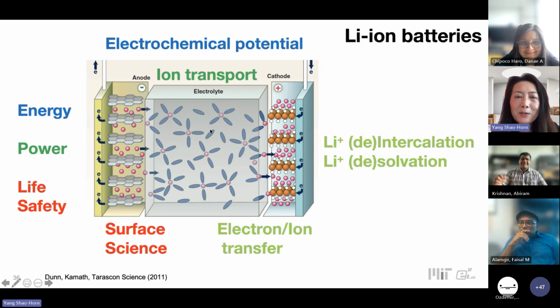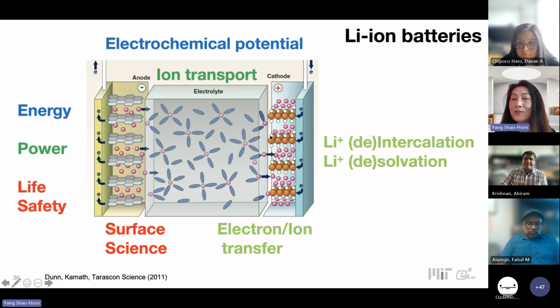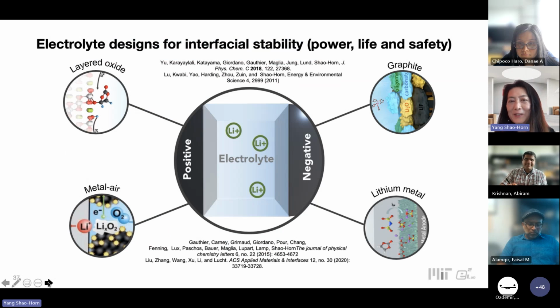Great. So in lithium-ion batteries, electrolytes play a very critical role. They not only influence ion transport, they influence the electrochemical potential, or the lithium redox, for either electrode on the absolute energy scale. The electron transfer at the interfaces influences the power and the energy of such a system, and the stability of the interface also influences the power, lifetime, and safety of such batteries. We would like to advocate that the electrolyte is a key enabler in order to commercialize new chemistry and new materials in lithium-ion and sodium-ion and beyond, as well as other chemistries such as lithium metal batteries and air or sulfur batteries.